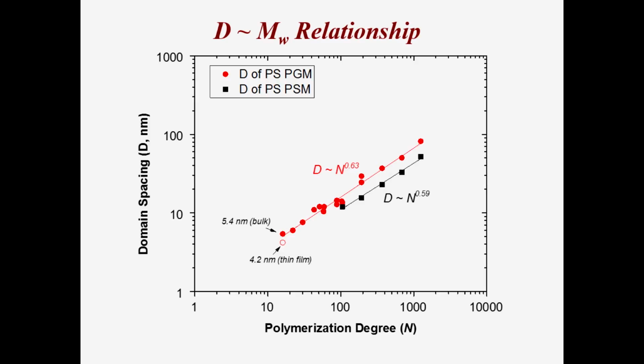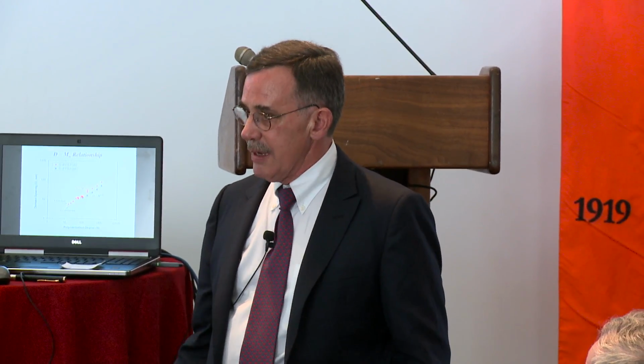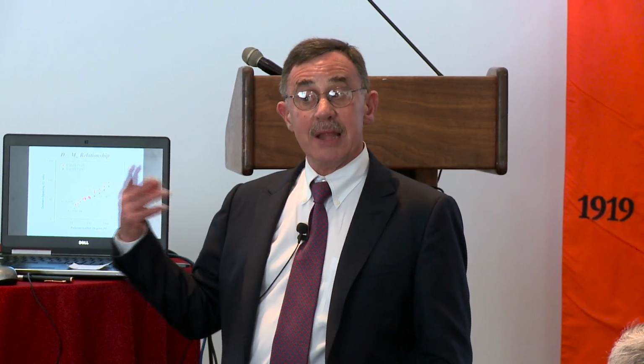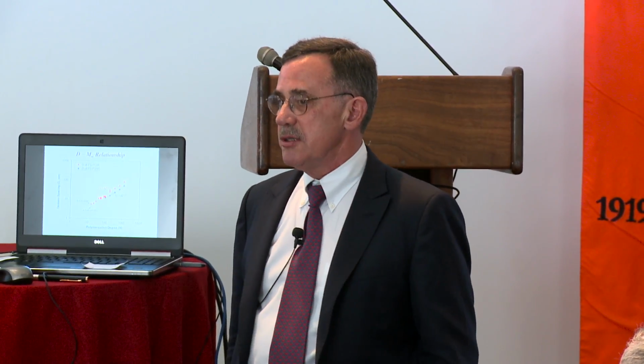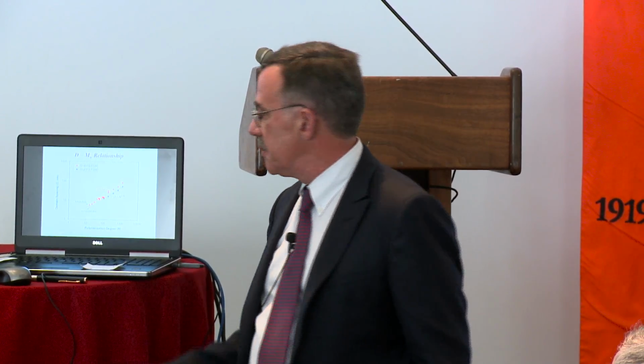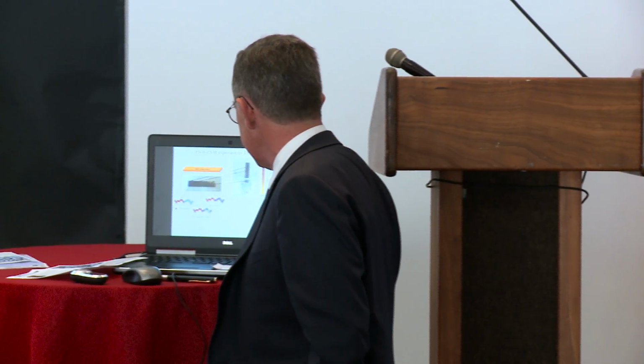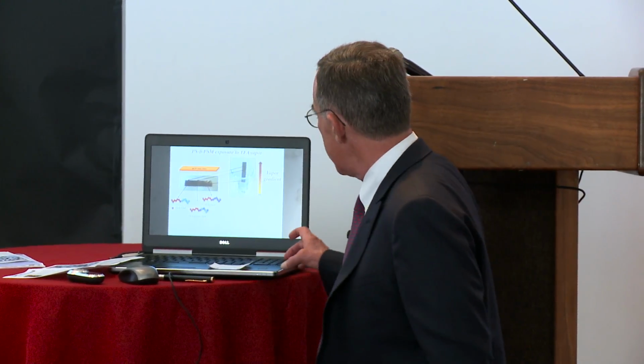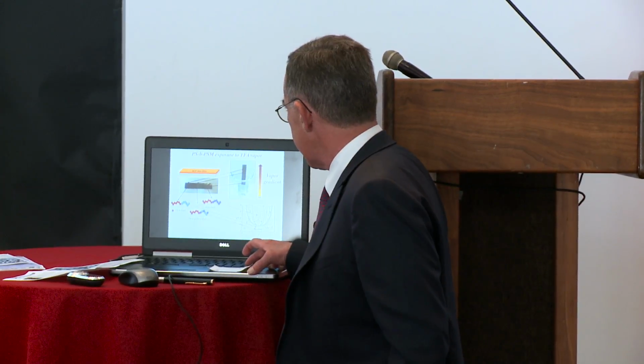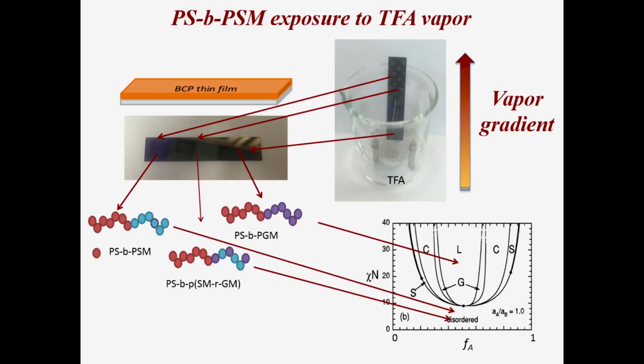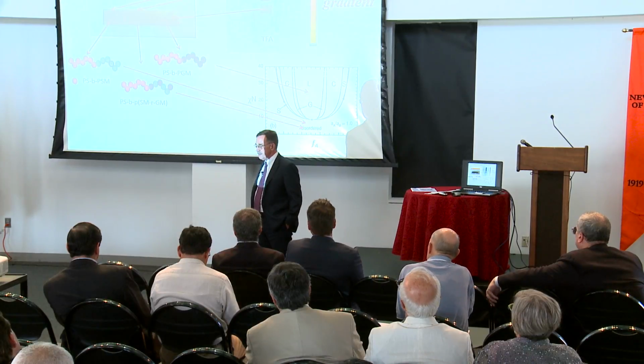Because I'm doing this now in the solid state, and now I can actually utilize the fact that I can use something like acetone, all right, to plasticize the polystyrene to be able to induce the lateral ordering. And I'm going to finish off with one last little trick. And the last little trick that you can use with these materials is that this happens to be a film where you cast the copolymer thin film disordered.